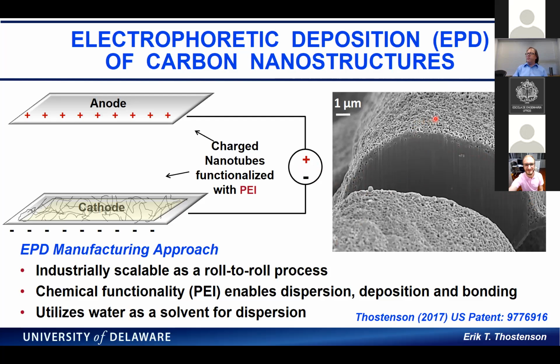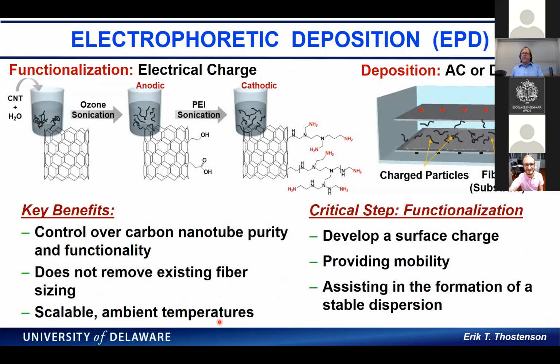coating. On the top, this is actually a porous nanocomposite coating. We're functionalizing these nanotubes with a dendrimer called polyethylenimine (PEI) that enables both the bonding and the dispersion, because that gives us the charge. It's also industrially scalable as a roll-to-roll process. One of my PhD students has recently developed a pilot line for making larger scale quantities. Right now we use it as a batch process. We also use water as a solvent, so it's more environmentally benign.